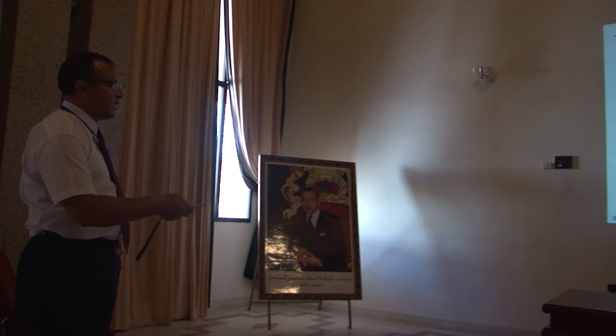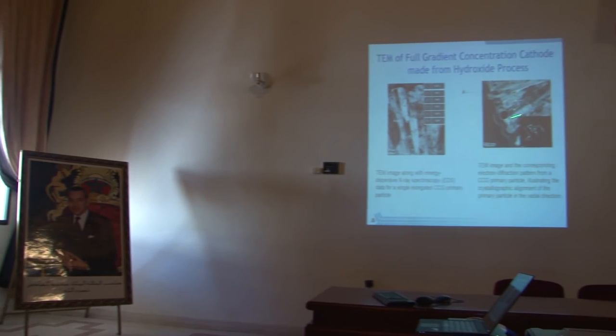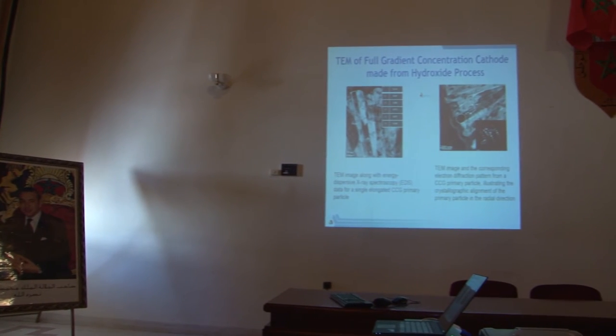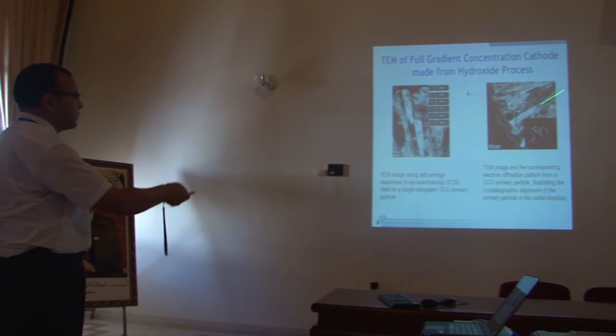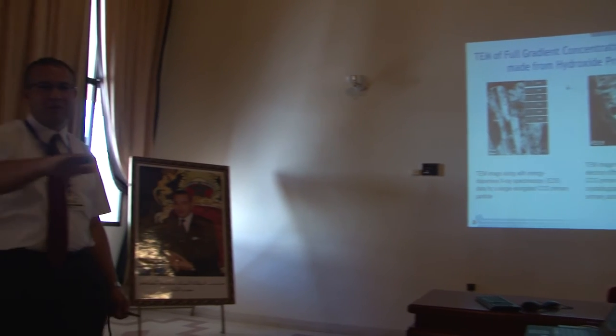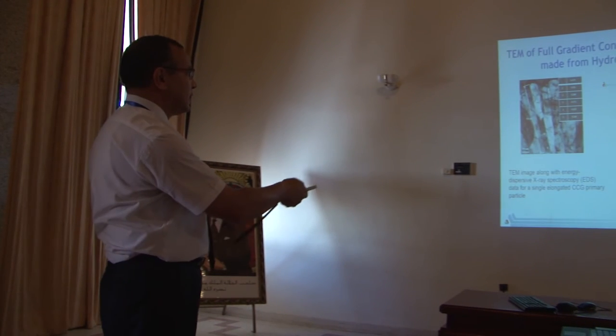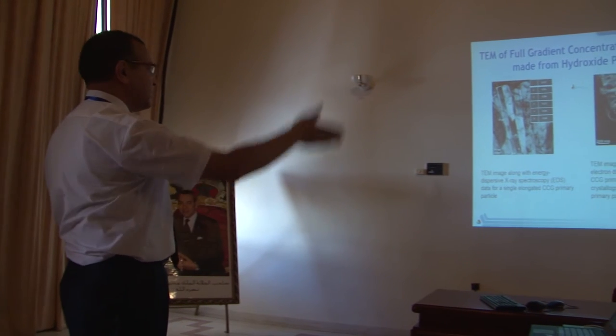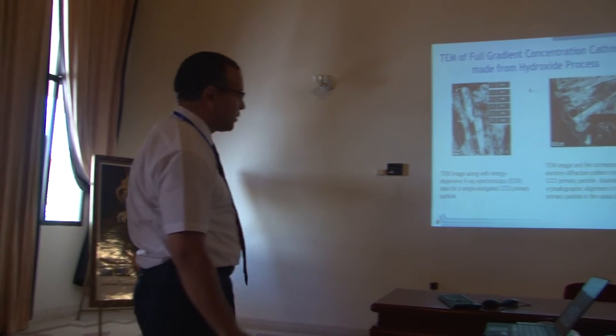And if you dig deeper, you can see clearly that there is a crystallographic alignment of the particle, for example. So here is the center, and this is outside. So instead of having lithium moving through the grain boundaries, it can actually move straight forward, because you have a path where the layered structure is in the radial direction of those rods.